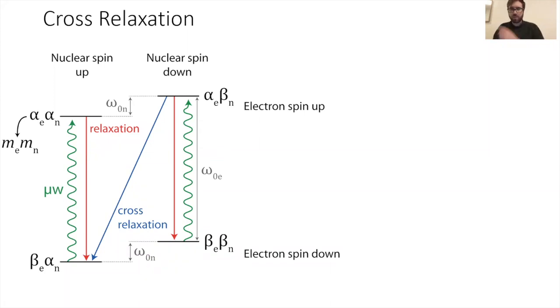This next one might be a quick answer, but how does the Overhauser DNP scale with applied microwave power? Is it linear or is it non-linear? Is it in the amount of enhancement? Presumably, yeah, the DNP enhancement. Although it's certainly, I would expect it to scale linearly with the amount of saturation you get. I'm not sure that the amount of saturation you get scales linearly with power. Do you know, Katerina? No, can't tell very well from our measurements because they're a little challenging sometimes. When you change the power, you change your peak position slightly. And you have to be quite careful doing these measurements. So we don't have a good answer for that now, I think. Okay.